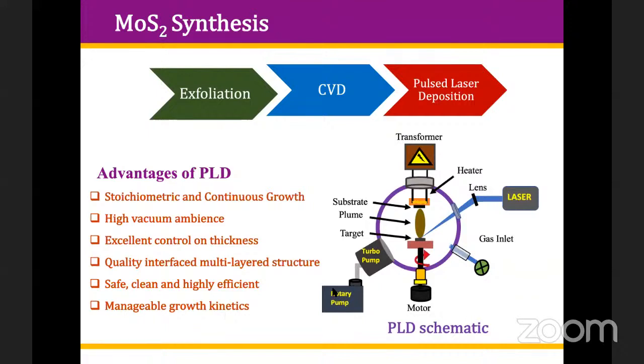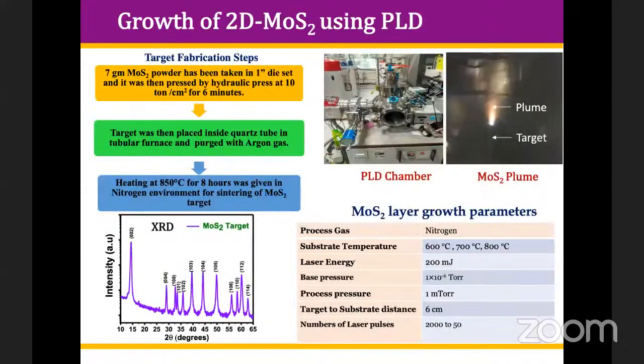So in the pulsed laser deposition technique, you need a high vacuum chamber in which you put a target of the material, like in this case, an MoS2 disk. Then at 45 degrees, you inject a high power pulsed laser beam. When the interaction occurs, a plume comes out, ejecting the material, and you can deposit it over the substrate. The substrate can be rotated to make a uniform coating, and you can also provide heating so that proper nucleation centers are there in the system. So this is just a basic idea about the pulsed laser deposition system.